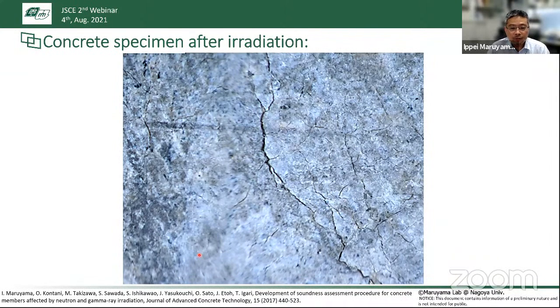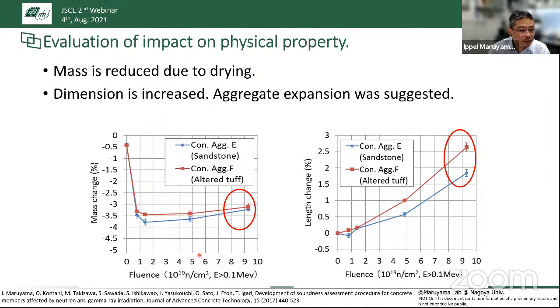First, we identified cracks on the surface of the concrete. This is evidence that something happens in the concrete after the irradiation. And these are the data of the mass change and the length change of the specimen after the neutron irradiation. The X-axis is the neutron fluence, meaning how many neutron particles attacked the concrete specimens. We see a large drying impact. The capsule maintained the pressure to keep a safe condition inside, and during the irradiation, vapor, oxygen, and hydrogen are produced due to the elevated temperature and the radiolysis. And the valve releases these elements from the capsule. Therefore, we see the drying impact during the irradiation.